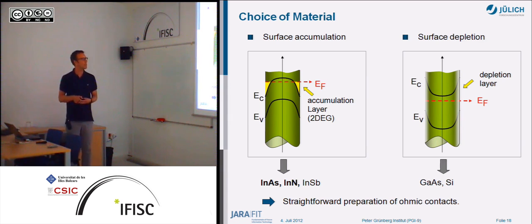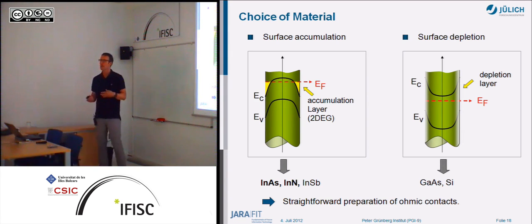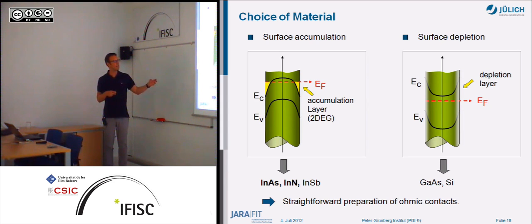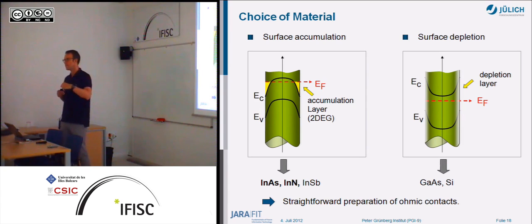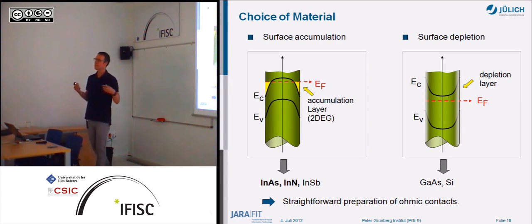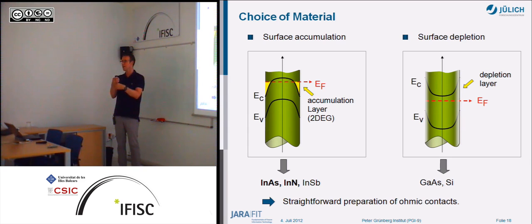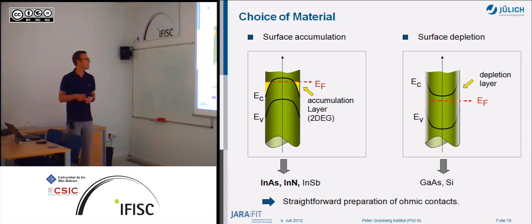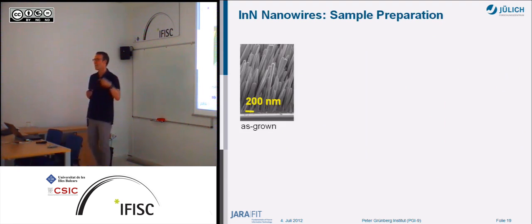If you compare that with gallium arsenide, for instance, you have the opposite because you have a different band structure. The electrons are not transferred into the bulk semiconductor, but into the surface state, and in that case you have a depletion layer. And you can imagine if you have this kind of semiconductor, then if the nanowire is smaller and smaller, you're losing all the electrons here because you have a complete depletion of the nanowire. So in this sense, it's the best choice to have these narrow bandgap semiconductors so that you can rely on the accumulation layer here, that you have a natural two-dimensional electron gas. If this electron gas is really as nice as I showed here, that's still something to discuss and still something to study. We do experiments on this, and we're still not sure how in detail this looks like.